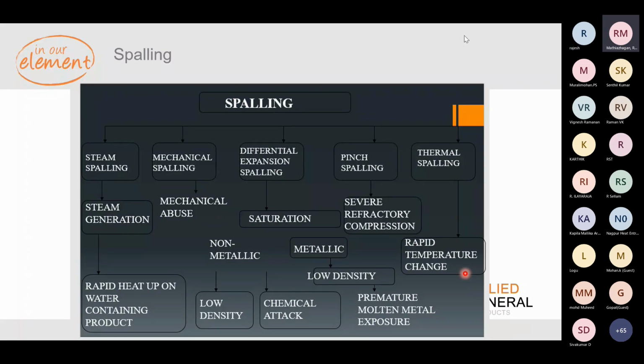For example, many people would have seen this in the bottom of the furnace. When the bottom of the former is not completely in contact with the refractory, if there's a bend or a curve or something concave, the refractory tries to expand to that level, and once the sintering operation is completely done, you can see a small popped up refractory at the bottom. So normally we suggest the customers ensure the bottom is completely flat and it is completely sitting over the refractory 100% to avoid these kind of pinch spallings. And thermal spalling is because of rapid temperature change during the operation.